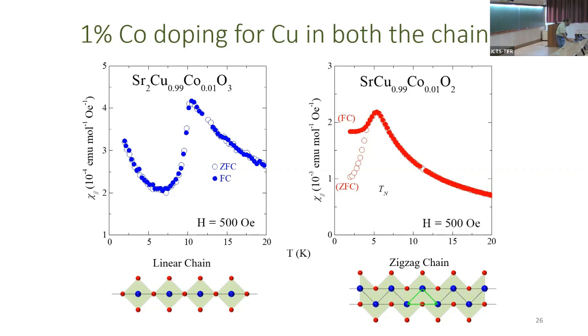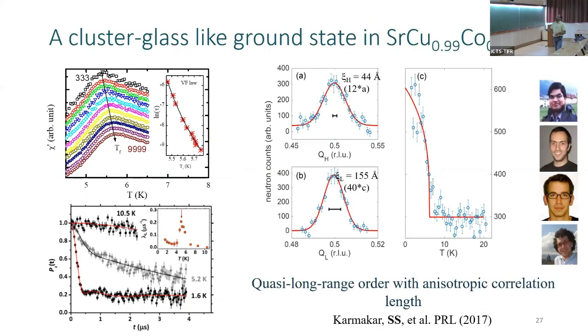presence of frustration. Now, in order to show this further, we did more detailed experiments, and these are actually reported here in this PRL paper. You get the characteristic frequency dependence, and from the mu-SR, we don't see oscillations, or you see very weak oscillations, which indicate that you have these puddles of ordered regions, which were probed by the neutron experiments. And you see that the puddles' size is about 12 unit cells perpendicular to the chain and about 40 unit cells in the direction of the chain.